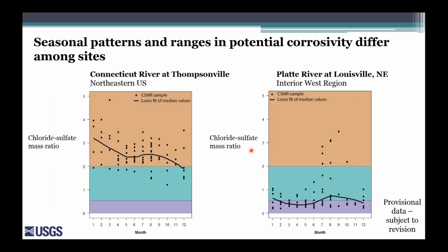So the temporal records from individual sites can also show important seasonal differences in the chloride to sulfate mass ratio. I'm displaying all of the chloride to sulfate mass ratio observations between 2010 and 2015 for 2 sites that were included in the status assessment. Months are indicated on the x-axis, the chloride to sulfate mass ratio is on the y-axis, and the individual points are showing individual observations by month over the status assessment period. The lines are showing a locally weighted regression that is meant to express the central tendencies of the observations.